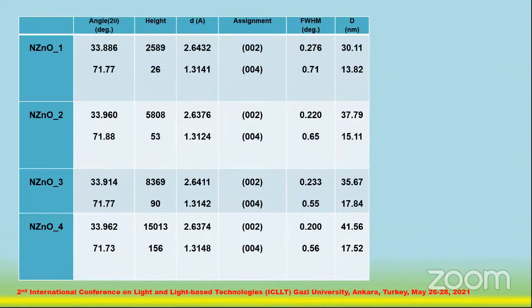Figure 1 shows that as the film thickness increases, the diffraction peaks became sharper, their intensity is enhanced, and their location changes. This behavior means that residual stresses are generated during the deposition process.